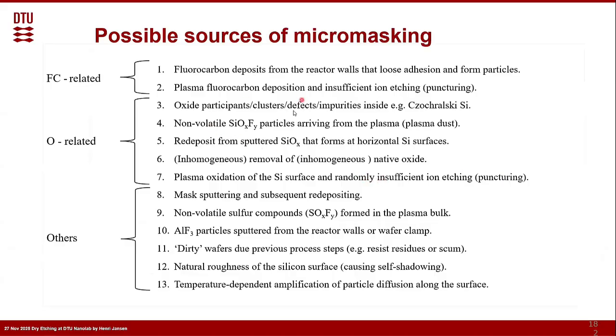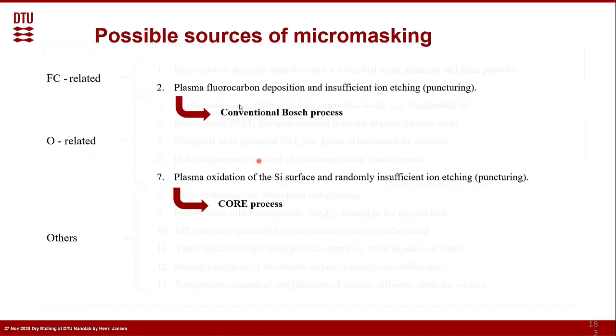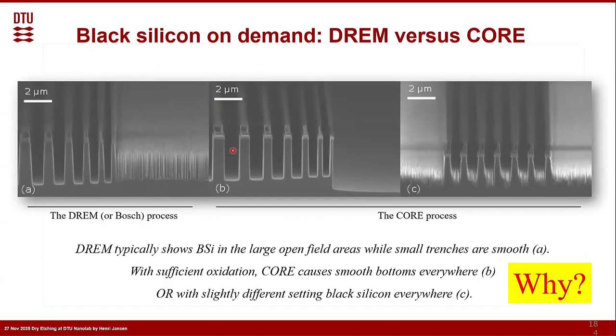Looking at the whole scheme, there were all kinds of possibilities where it's coming from: the reactors, maybe dirty wafers, but two of them are always there. You can get rid of all the others, but if you don't, in the switch process, if you don't remove your oxide or fluorocarbon at the bottom of your structures during the removal step correctly, you will create black silicon. And then we look further. We see that there are two distinct differences between the Bosch process and the core process. For the Bosch process, we see sometimes in big open fields a lot of grass, whereas the smaller structures are nice. But for the core process, it's either everything is clean or everything is black silicon. So in the big open structures, but also in the smaller ones.